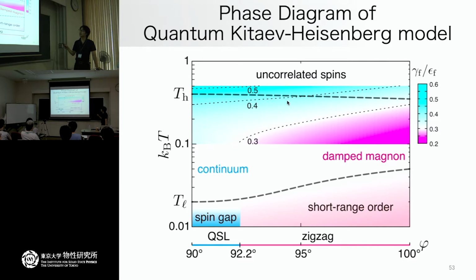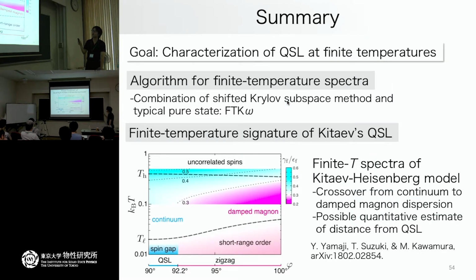As a typical example from experiment, the Kitaev-Heisenberg model at finite temperature has a scale of 0.1. So in this sense, if you lower the temperature and this number goes below 0.3, and becomes more or less below 0.2, then it describes the damped magnon phase with the magnetically ordered ground state. So if you measure the ratio between the peak width and the peak energy scale, this gives you the finite temperature signature of the spin liquid phase, and it may give you some quantitative distance from the spin liquid phase in your real compound.